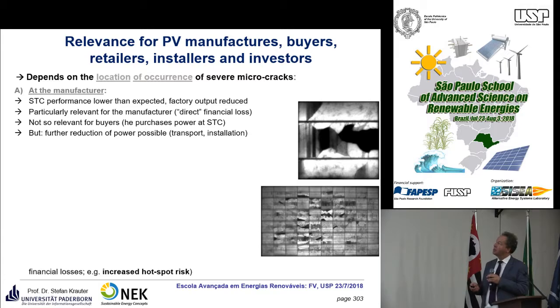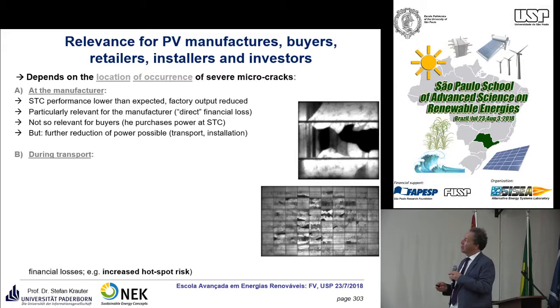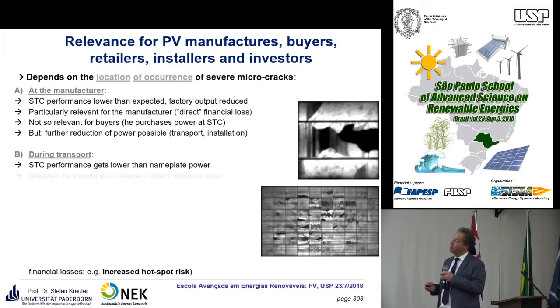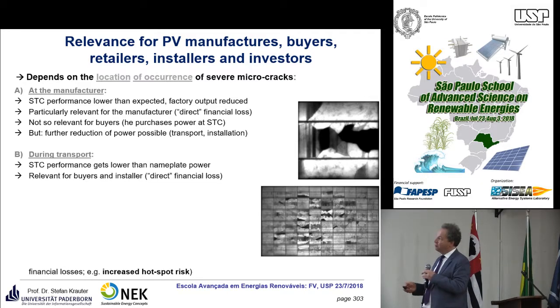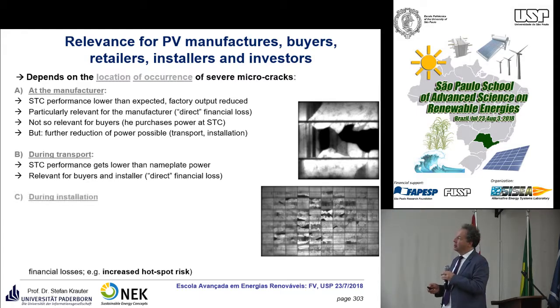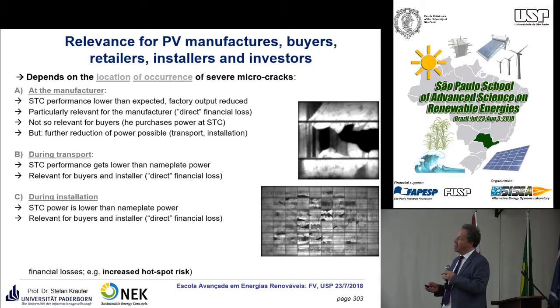Therefore, it's quite good to do this electroluminescence analysis. Also during transport, the STC performance can get lower than the nameplate power. This is also relevant for buyers because you paid money for your STC power and now you have reduced power output. So it's a direct financial loss for you. During installation it is about the same. So it's relevant for buyers and installers, a direct financial loss. And operating in the field, the energy yield is lower than expected.